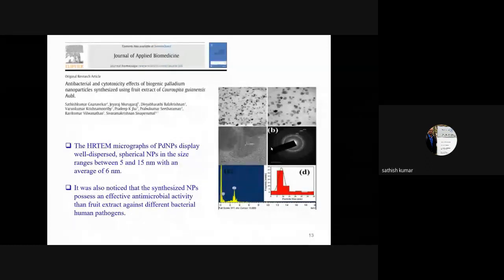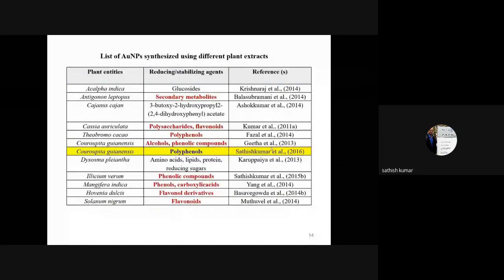Here also, it was very clearly evident that as compared to the plant extract, the synthesized nanoparticles have more antibacterial as well as anti-cancerous properties. So based on our preliminary screening with different plant extracts and the plant extracts that have been reported by different research groups worldwide, it was clearly evident that in almost 80% of plant-mediated synthesis, the polyphenols play a major role in the reduction and stabilization of the nanoparticles.